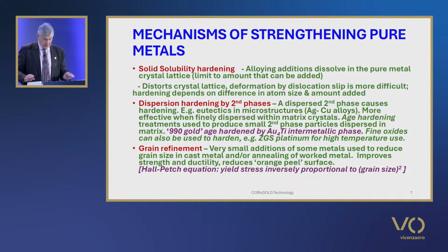In dispersion hardening by second phases, when a second phase is dispersed in the metal, it will cause some hardening. Alloys that form eutectics in their microstructure, such as the silver-copper alloys, are good examples here. However, if the second phase is present as very small particles dispersed within the grains or crystals of the parent phase, these impede the movement of dislocations during deformation and cause considerable hardening.